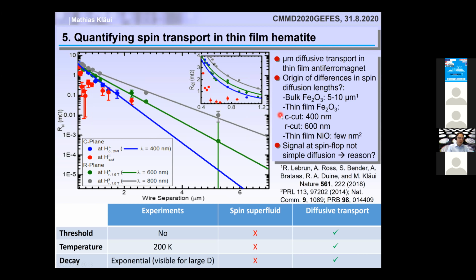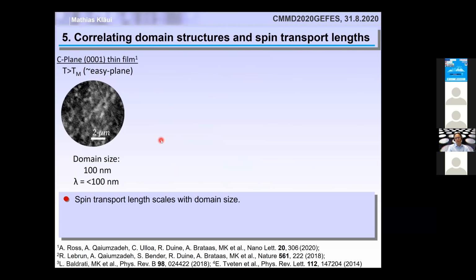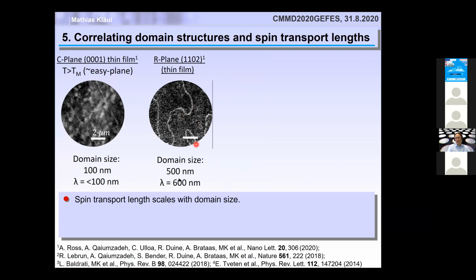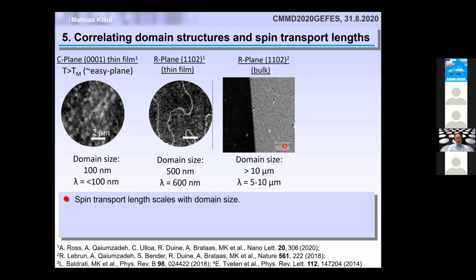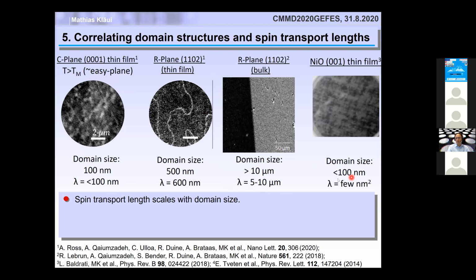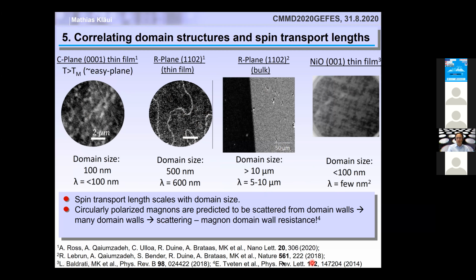And so to check where this comes from, we did imaging of the spin structure, and we found that if we have many domains, many domain walls, we get a very short length scale. If you have domain sizes of a few hundred nanometers, we also get spin transport length scales of a few hundred nanometers. And if you have domains of 50 microns or larger, we get spin transport length scales of a few microns. And if you have many small domains, we get a very short spin transport length scale. And this fits nicely a theory paper which was published here, where due to scattering of the magnons, you have a reduced transport length scale, and so something like magnon domain wall resistance. And so this means that by the domain walls, we can govern the spin transport length in these systems.